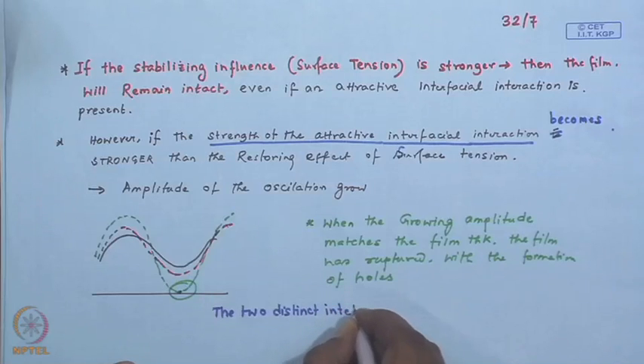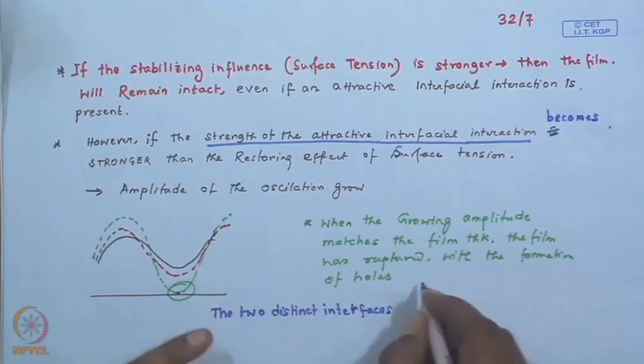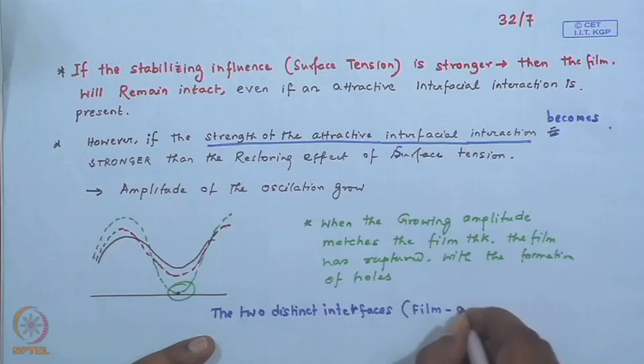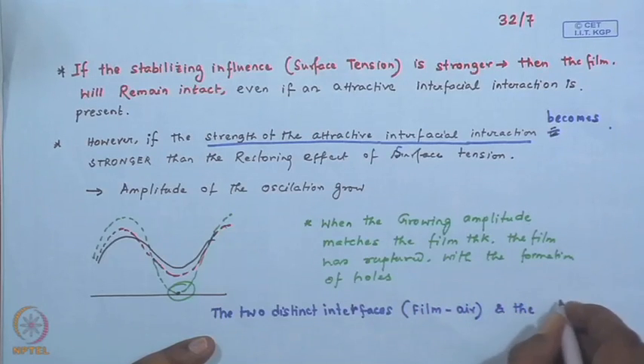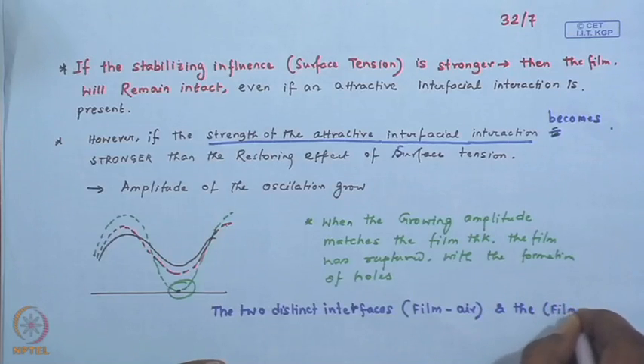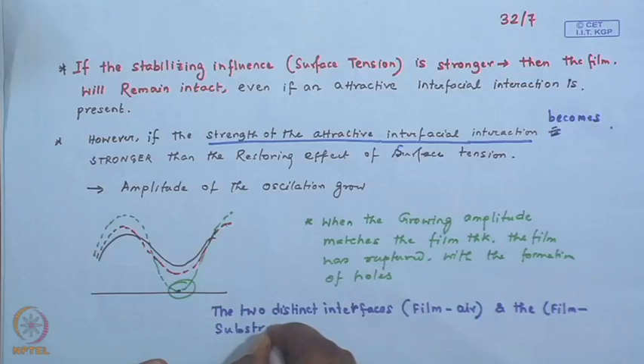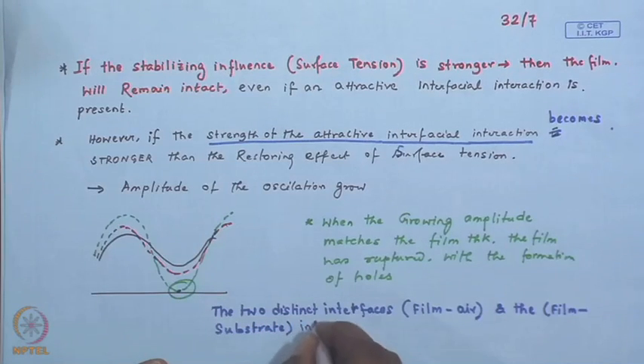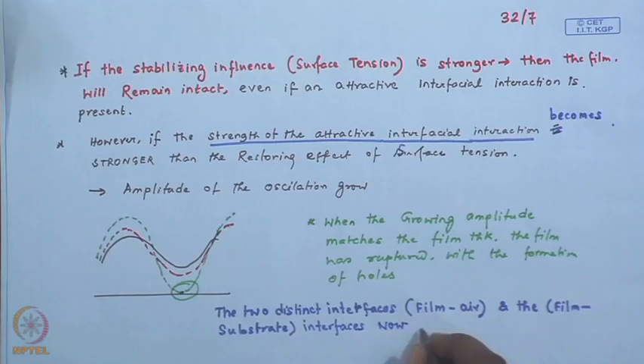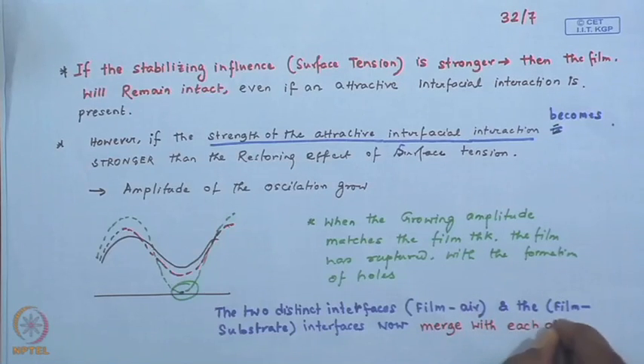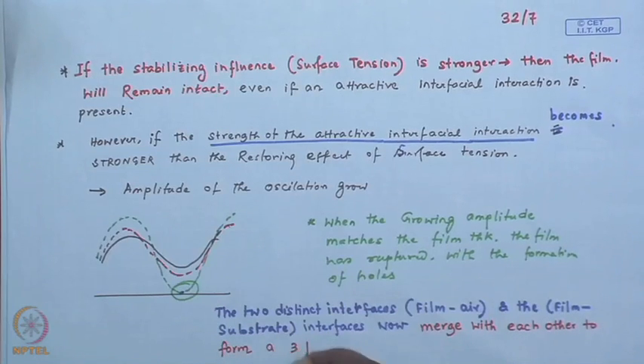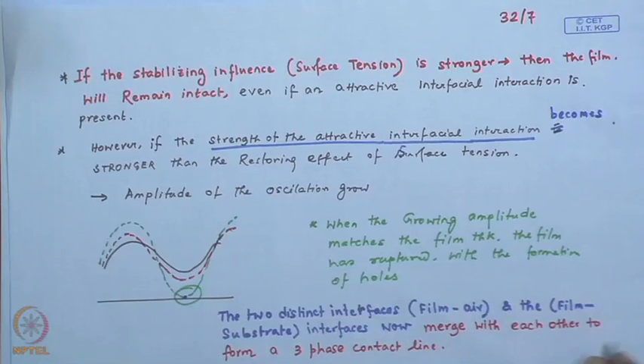distinct interfaces, that is the film-air and the film-substrate interfaces, now merge with each other to form a 3 phase contact line around the hole.